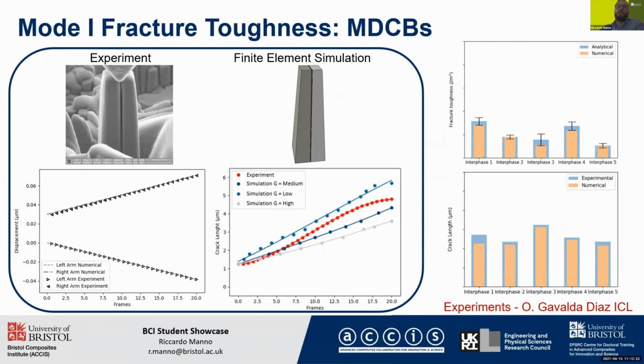Displacement of the beams are fed to the model, and the crack length is then compared with the experimental result, allowing us to define the mode 1 toughness. You can see on the right-hand side of the slide the comparison between experimental and numerical results in terms of crack length, whereas values of toughness instead have been compared with analytical models.